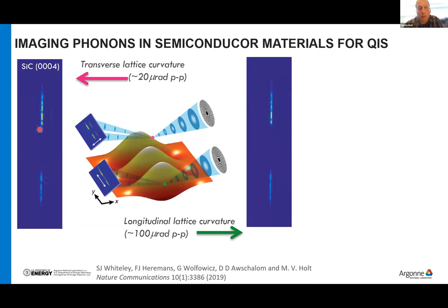There's this small curvature change given by the Gaussian focusing of the acoustic wave, and this larger curvature change driven by the progression of the acoustic wave. But both of these are order microrads. So we're basically invisible to all other kinds of microscopy that isn't really caring about crystallographic mirror planes.